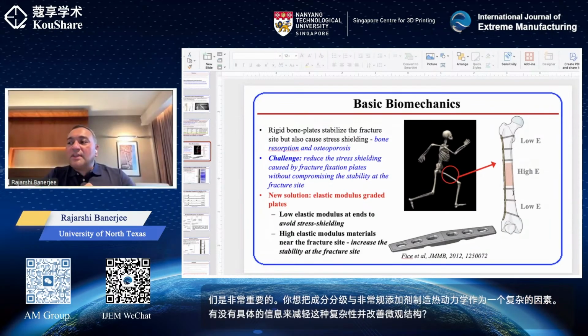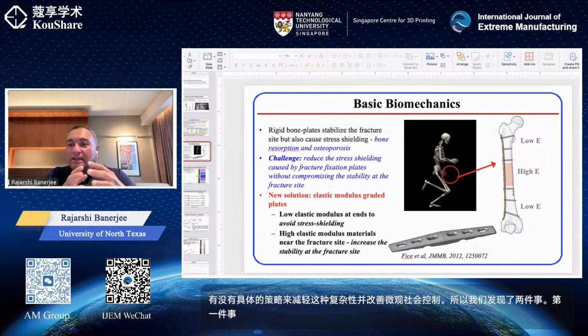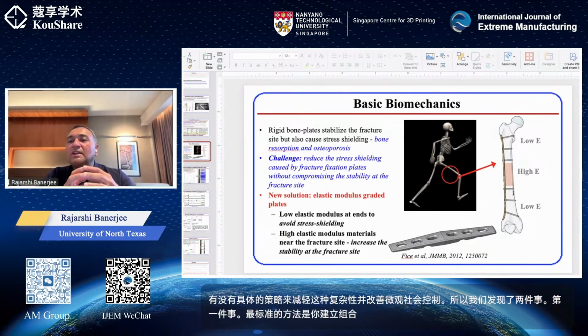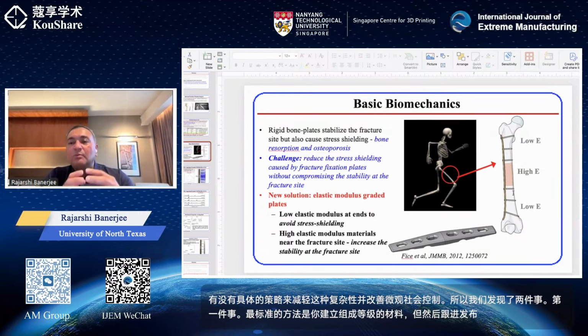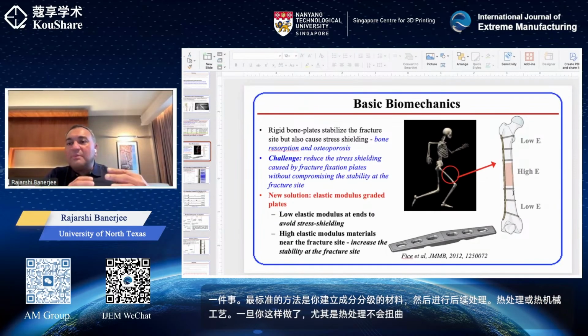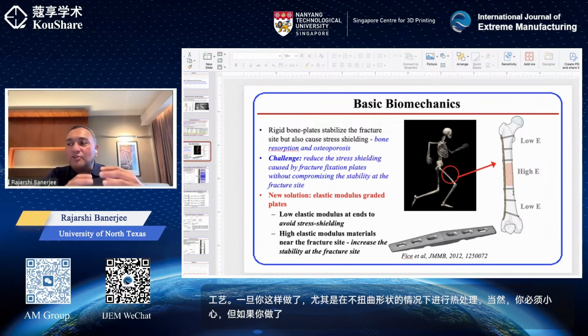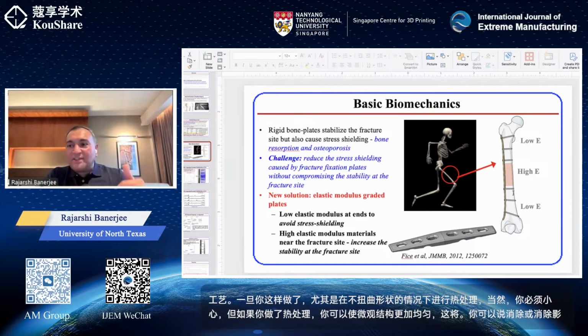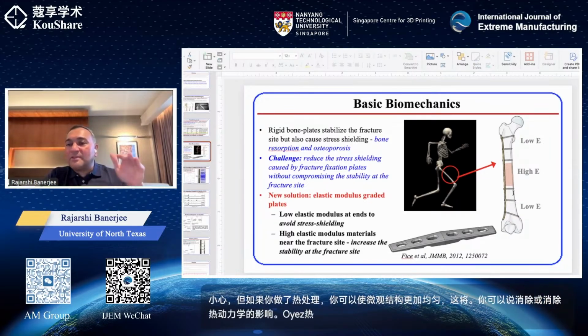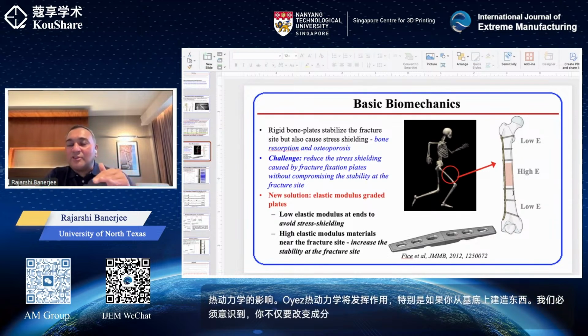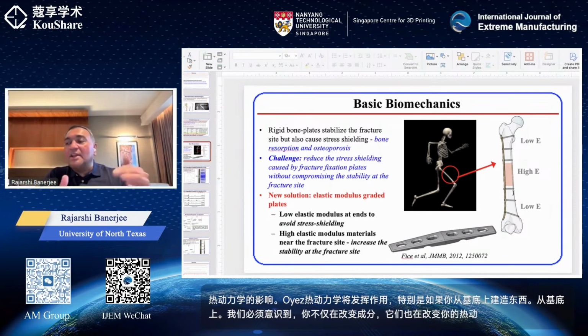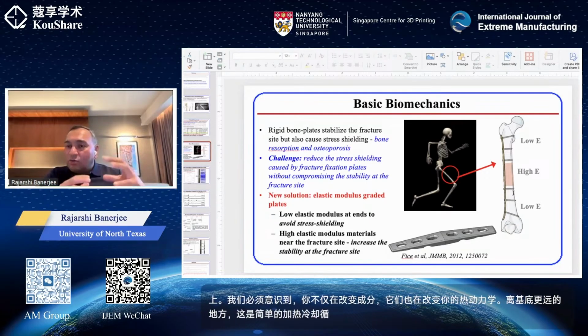Yes, so there are two things that we found. The first thing, the most standard way, is you build the compositionally graded material, but then follow up with post-processing heat treatment or thermomechanical processing. Once you do that, especially heat treatments, without distorting the shape, of course, you have to be careful. But if you do a heat treatment, you can go back to a more homogenized microstructure, which will, you might say, obviate or remove the effects from the thermokinetics. So yes, the thermokinetics will play a role, especially if you're building something from a substrate. We have to be aware that not only are you changing the composition, you're also changing the thermokinetics as you go further away from the substrate. This is the simple heating cooling cycles. So if you want to remove that effect, you can do post-process heat treatment.